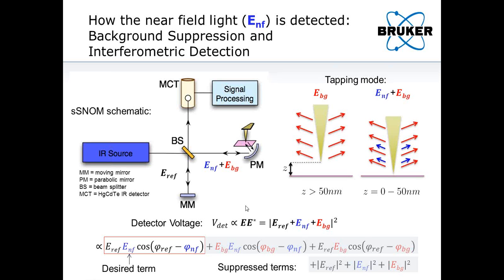So using those two tricks, a large reference field and oscillation of the tip, you can basically isolate this desired term from all of these other terms. And that's how experimentally people measure the near field term in scattering SNOM.